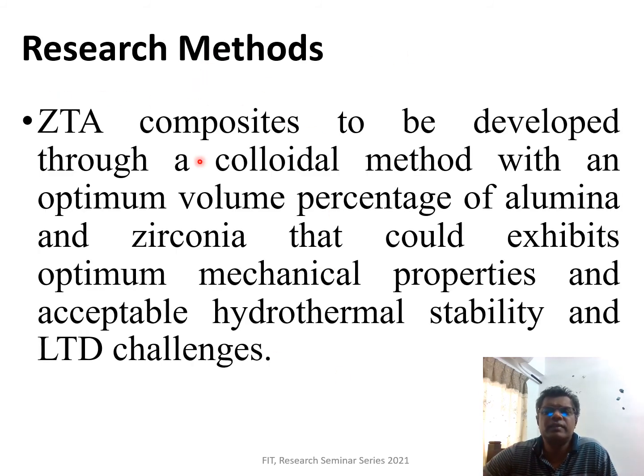So, research method. The technique we're going to use to develop the ZTA composite is a colloidal method. Compared to the normal powder processing, we use a colloidal method with an optimum volume percentage of alumina zirconia to be found that could exhibit optimum mechanical properties and acceptable hydrothermal stability.